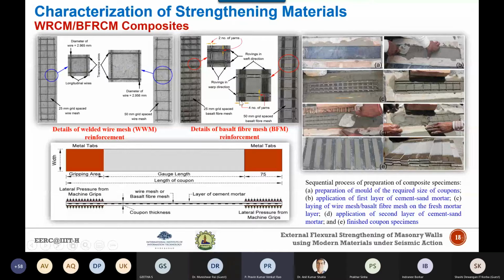Now, according to AC 434 guidelines, here you can see that the brown color metal tabs have been bonded on both sides of the specimen, especially in the gripping zone, using an epoxy glue. And this arrangement basically avoids damage to the specimen by the hydraulic grips in the test machine, and improves the stress transfer mechanism at the reinforcement mortar interface.